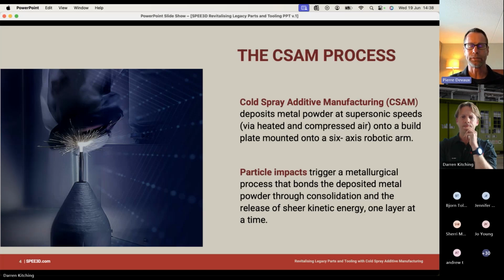But about 10 years ago, SPEE3D decided to try to apply cold spray for the manufacturing process, or cold spray additive manufacturing. Basically, what we do is we take a rocket nozzle, we accelerate heated air through it at about Mach 3, Mach 4, and the metal powders basically collide into the substrate. You can see it in this little picture right here. It shoots this jet of air with metal powder particles inside, and just the kinetic energy of the powder hitting the substrate, it binds the powder together into a part. So that's the mechanical process. There's obviously a software side of things, as Darren mentioned. We take the STL, we run it through our simulation software, and then it generates the tool path for the robotic arm to move and print the part layer by layer. So that's how it works.